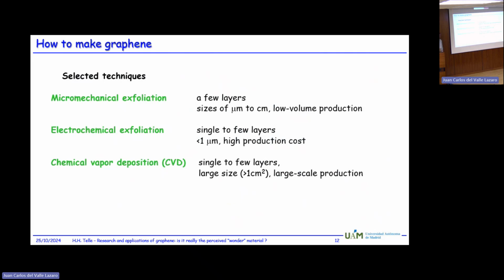Then you have, in addition to that, the electrochemical preparation. And with that, it is very simple and straightforward to generate single layers of graphene. But the size of these particles is normally very small. And also, it's relatively costly to produce that, in particular, the solvents you actually need for this. And then the third most common procedure today, which is applied by the majority of companies who produce graphene, is chemical vapor deposition. And again, the advantage of this method is that you can do large-scale production and large sizes of samples, and you can do very thin layers indeed.